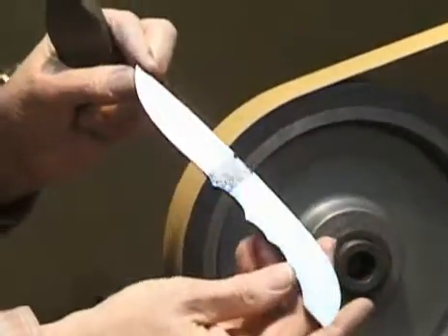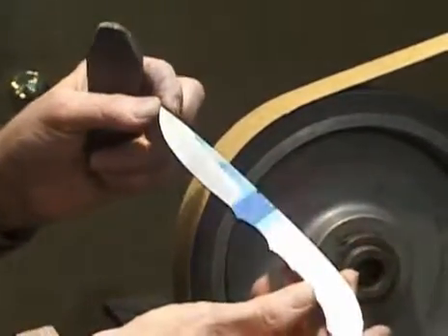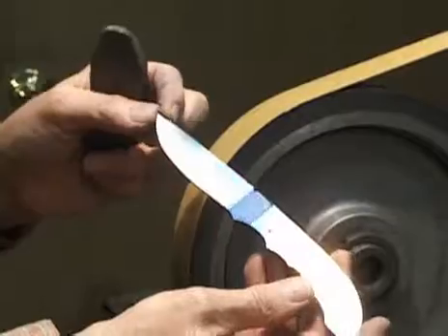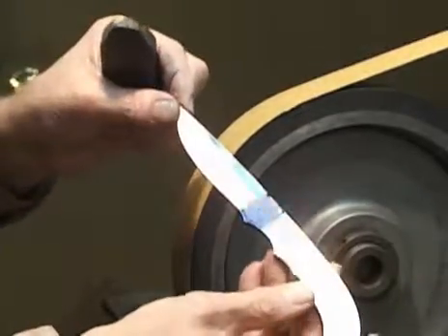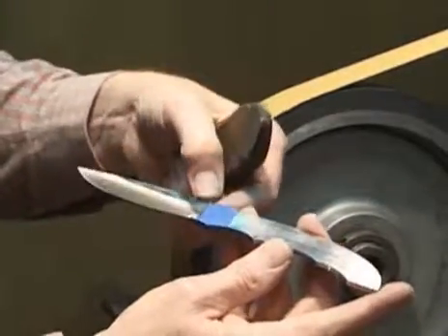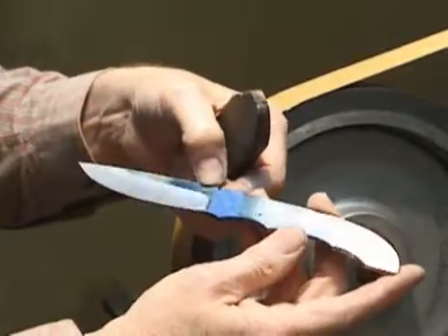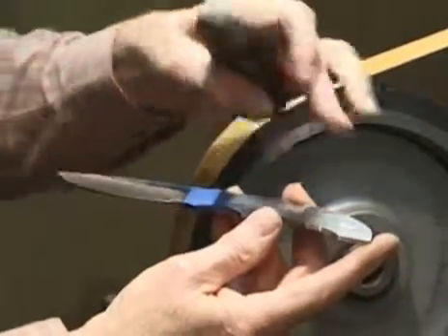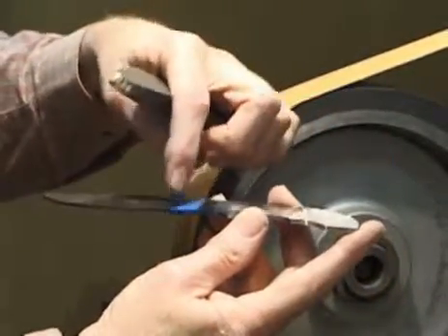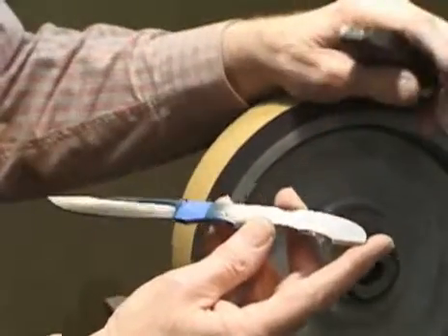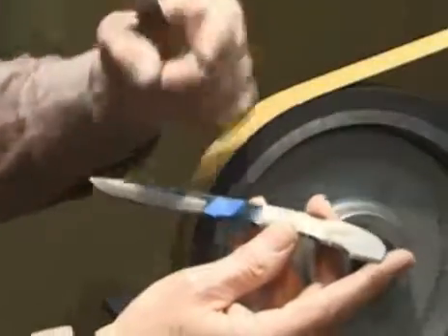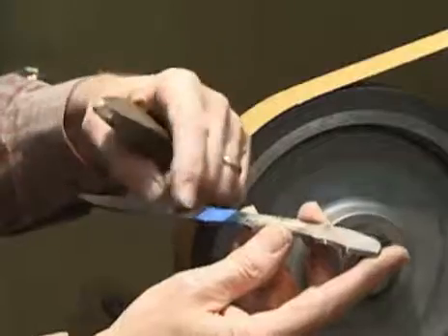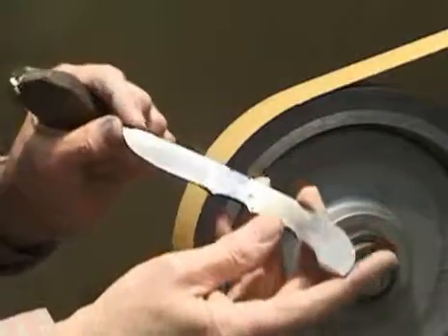That was about 10 or 12 passes on that blade, and you can see that I've got a good deep hollow grind established. I'm going to grind a little bit farther up on this blade, but remember, this is not heat treated. I still have to drill the holes in the blade for my guard and my handle, so I'm probably going to match the other side to this one, and then I'm going to stop.